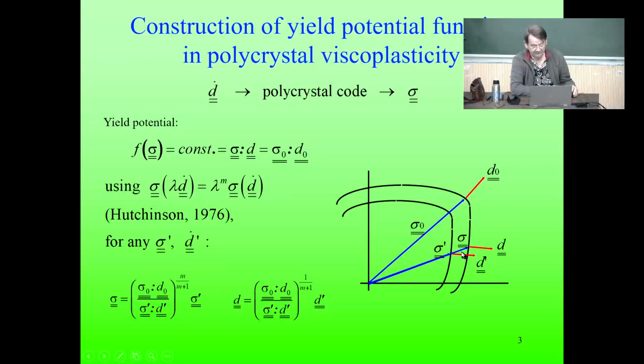Now, the complication is that for a forming limit diagram, perturbation theory, we still need the yield surface because we would like to approximate in this perturbation theory. We need to put it fully analytical so that we can apply our perturbation equation on all the material behavior. So there is no use for a non-analytical yield surface or yield potential. So we are going to fit locally the yield potential with an ellipsoid, the so-called Hill ellipsoid. This is why we need to define well the so-called yield potential function.